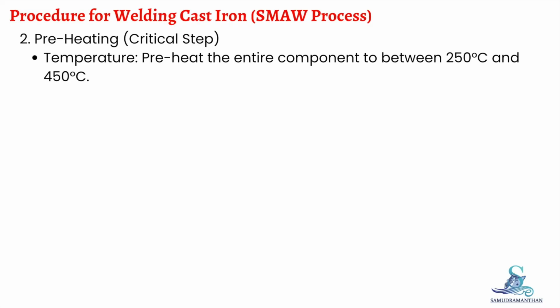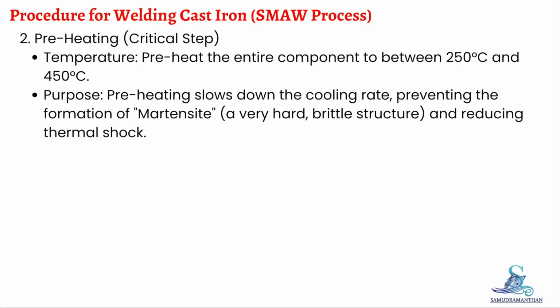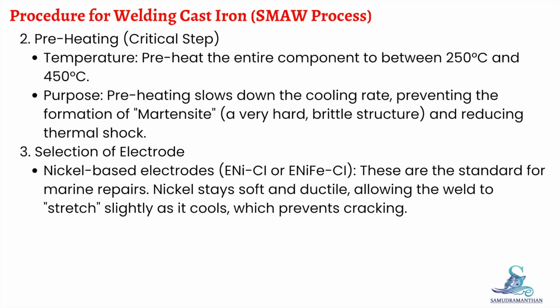Preheat the entire component to between 250 degrees C and 450 degrees C. Purpose. Preheating slows down the cooling rate, preventing the formation of Martensite, a very hard, brittle structure, and reducing thermal shock. Selection of electrode. Nickel-based electrodes.